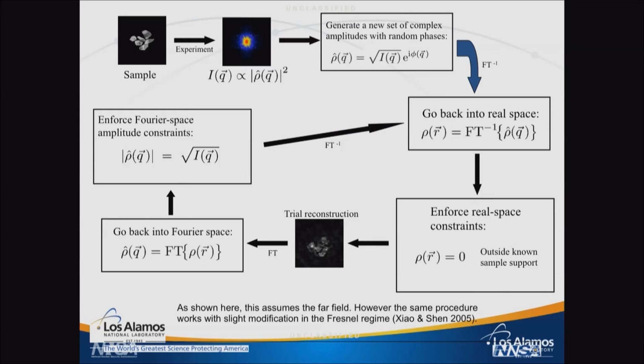So again, we start with some sample, something that you want to image, and we scatter off of it, and we get an intensity form onto a detector downstream. And that, of course, doesn't look anything at all like that. What we've measured is the norm, the absolute value, of the complex field downstream. Okay, so we basically take that field of amplitudes and we randomly assign a complex phase to every pixel in it.